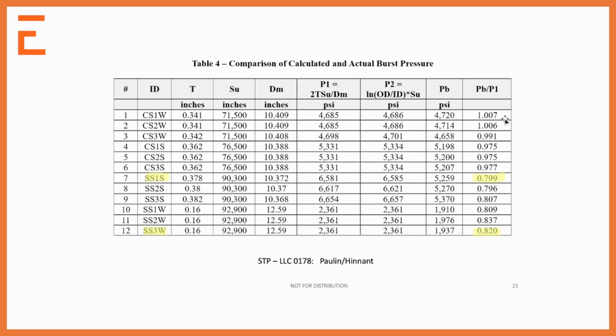And these are just like pressure burst tests? Right. You fail, pressurize it up until you lose pressure capacity, until you get from what's inside the pipe to outside the pipe, because that's the danger. And so here's all the carbon steel. So you can see the ratios. The ratios are all very close to 1. Here's the stainless steel. It drops down. 20% less.